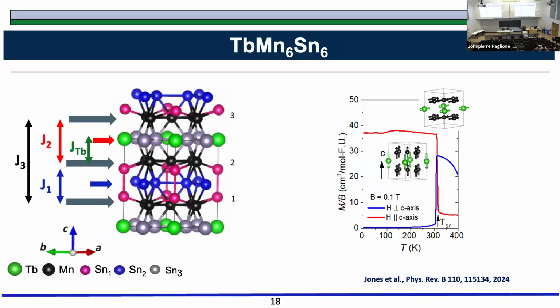And in this case, because of this additional interaction, these elements want to be parallel. The manganese wants to be ferromagnetic in each layer. Terbium wants to be ferromagnetic in each layer, but they are pointing in opposite directions. That kind of structure is called a ferrimagnetic structure. And what was very interesting about this compound is that it orders at about 420 with this kind of in-plane ferromagnetic order.